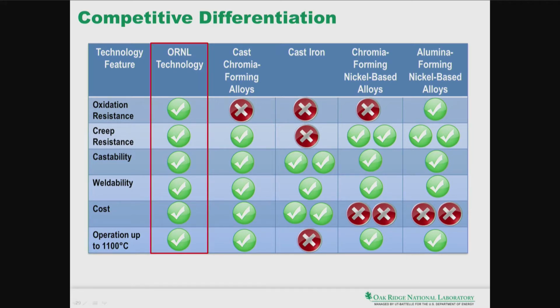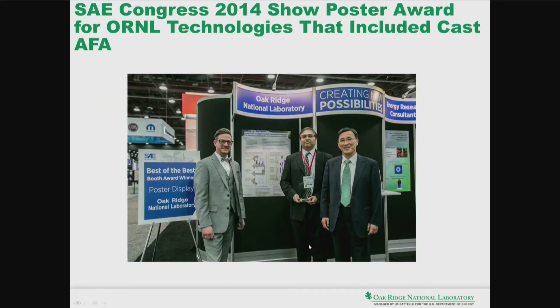And in terms of competing with the nickel-based alloys, as you can see on the right-hand side here, the cost is a big benefit as far as our alloys are concerned. And as I showed you in a couple of plots, the oxidation performance is comparable at the temperatures we have tested with some of the higher nickel alloys, which is very encouraging from the perspective of applications. Of course, in terms of cast iron in the exhaust manifold, we have much better oxidation resistance and creep resistance, with the castability of cast iron and the cost being the favored things for cast iron. Of course, its higher temperature operation is very limited.